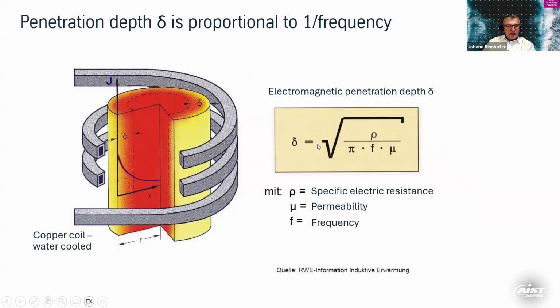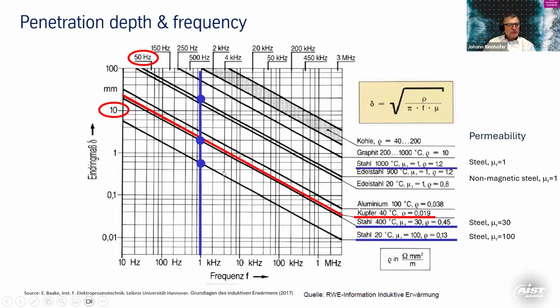The penetration depth you can calculate. It is proportional to the electric resistance of the material. Steel is good. Copper has a very low resistance, so that would give a very thin penetration depth. And very important, it is inversely proportional to the frequency, so 1 divided by frequency, and also to the permeability of the material. So what does that mean? You have different penetration depth data. For example, you can have 10 millimeters in certain conditions, at certain frequencies, and so on.